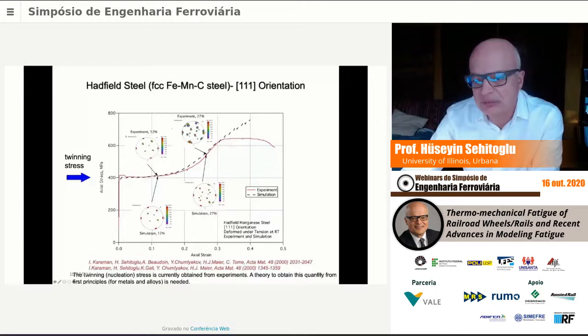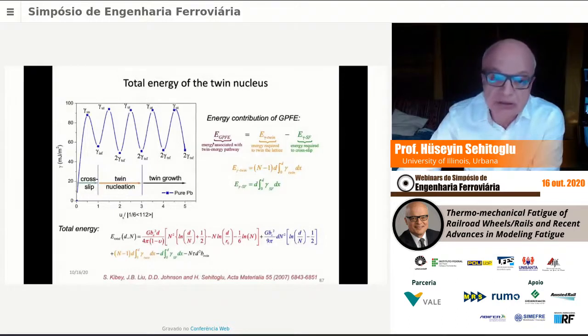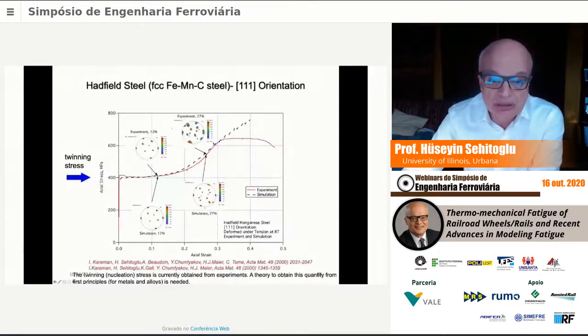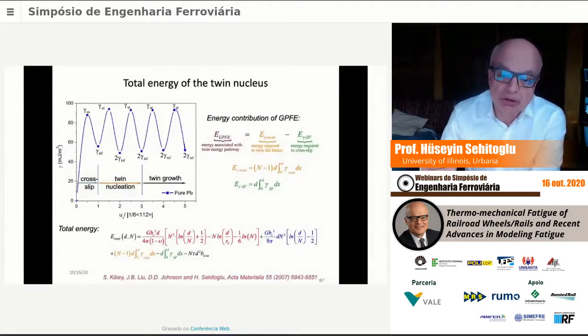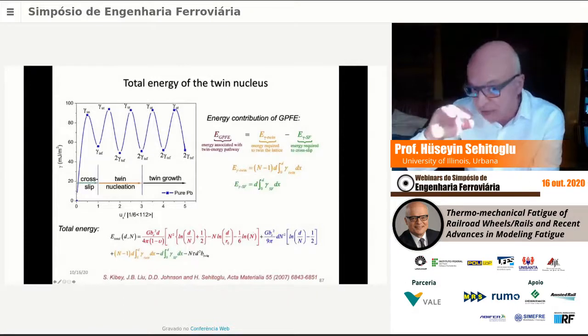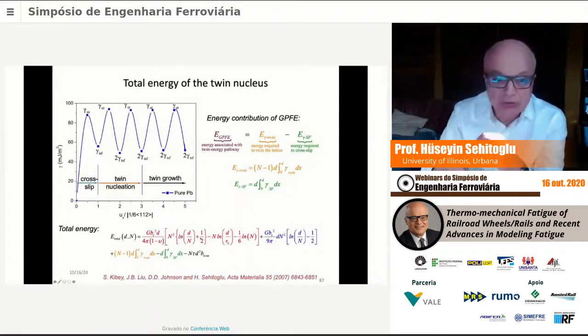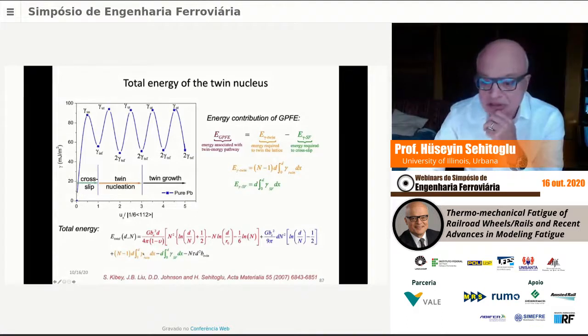And these are also called Hadfield steels, Hadfield manganese steels. We show here that we can predict their twinning stress. And the beauty of these materials is they show an upward curvature, which is unusual because the upward curvature typically is not observed. You know, we talk about downward curvature, but in these, because of the twin-twin interactions, we're getting, again, this was published in 2007, we are trying to predict this twinning stress, which is here.